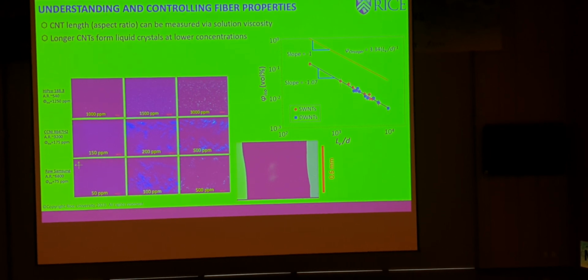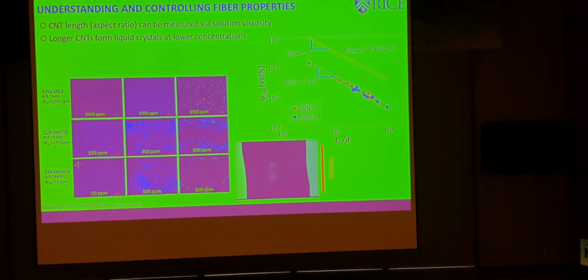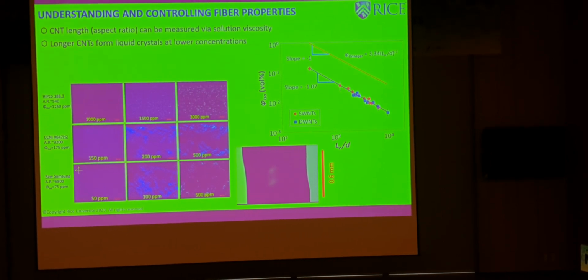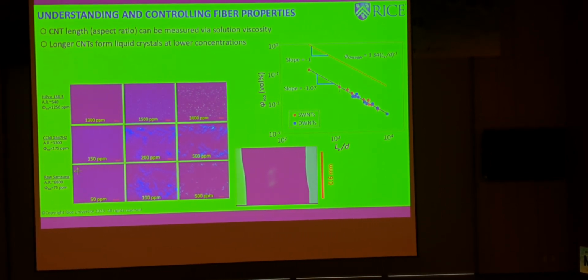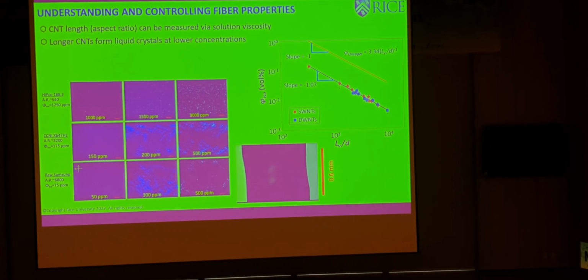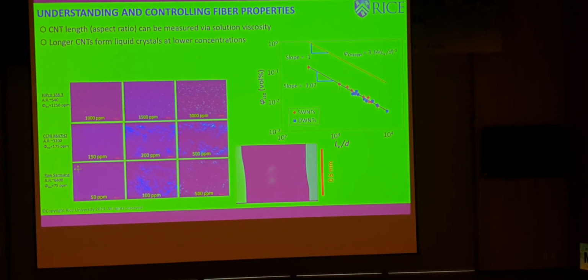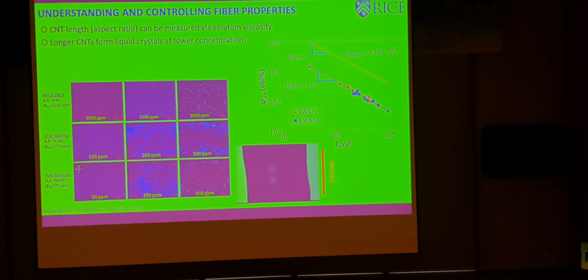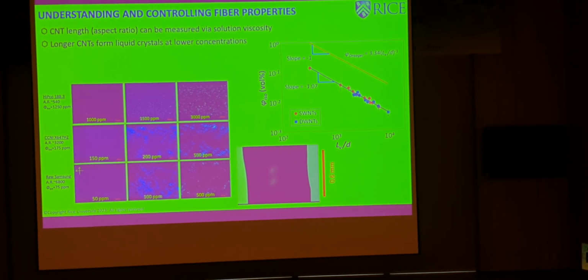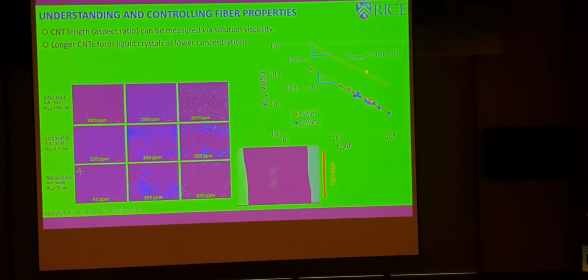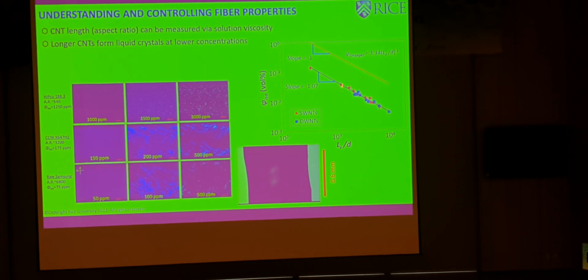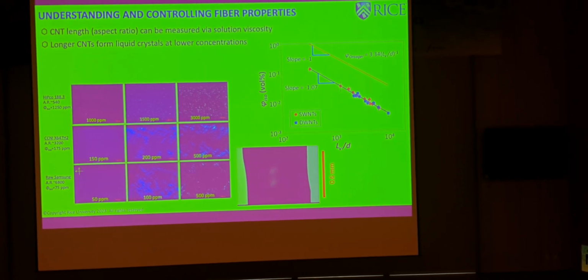It turns out that when you're at a low concentration, you can actually measure length by looking at the viscosity of a droplet of carbon nanotube solution that's being stretched. You can back out the viscosity from this method, and from the viscosity you can get the length. So you can get the length two ways, one by viscosity, another one by using the transition to liquid crystal. The distance between this line, which is the theoretical Onsager line, and this line is due to polydispersity of the samples.